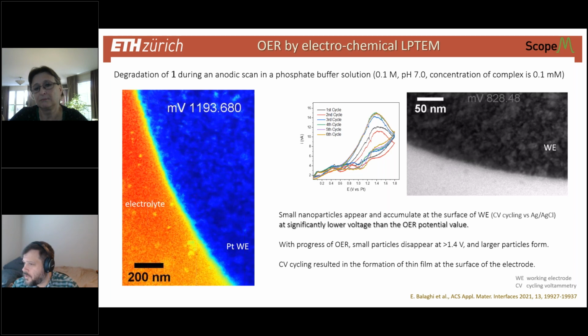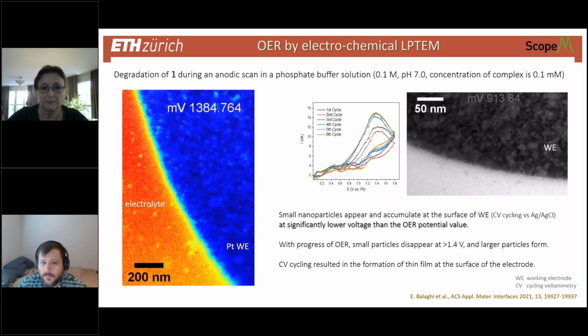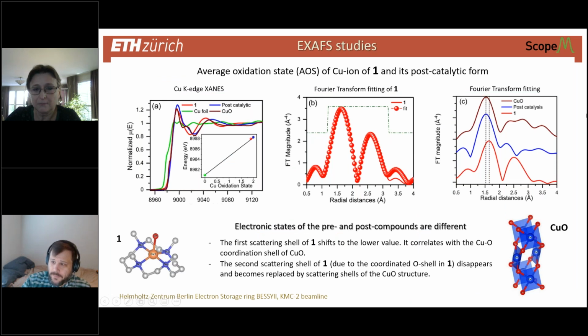We have a question on the synchrotron experiments, asking whether they were done with the samples still on the Protochips holder. No, of course not. The specimen was a post-catalytic specimen from offline work. It was an ex situ reaction, and they analyzed it there. It was not a TEM specimen, not literally the same material, but it fits pretty well, I have to say. So straightforward phase analysis fits so well with the structure that EXAFS reveals.